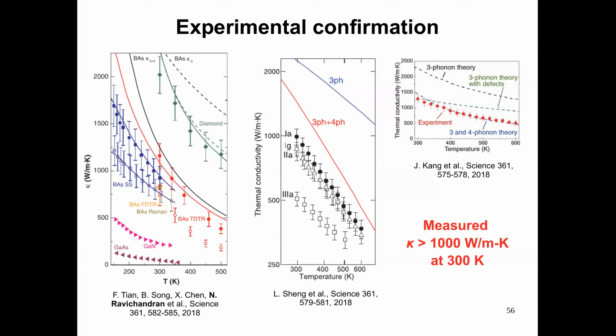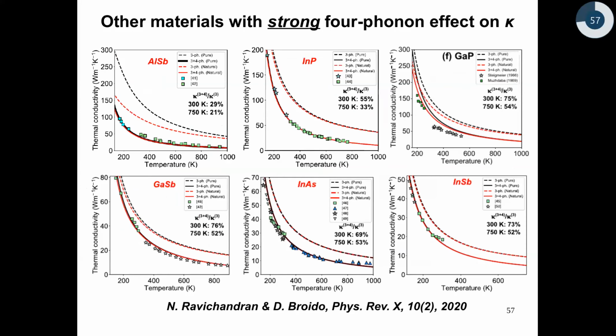There's also independent work which shows that boron arsenide has similar electronic properties to that of silicon. So now you have a material which is as good an electronic material as silicon, but 6 times a better heat conductor than silicon. So you can really envision passively cooled electronic materials with boron arsenide. There are other materials also. Boron arsenide is not the only case where 4 phonon scattering is important.